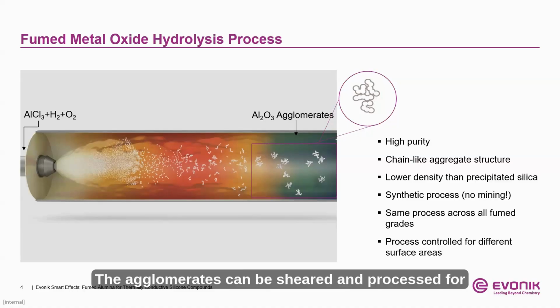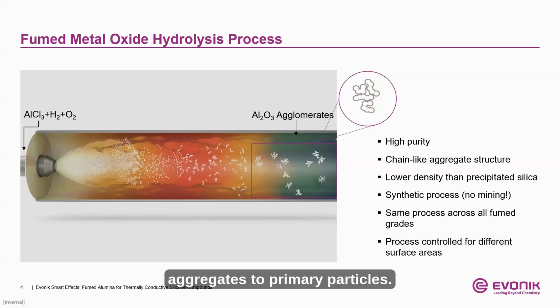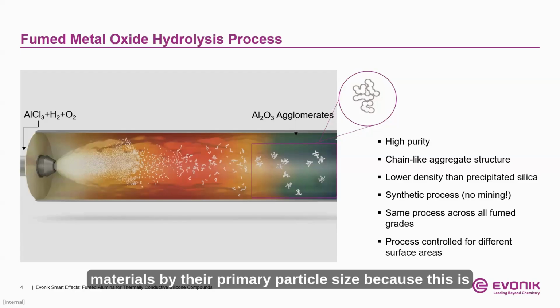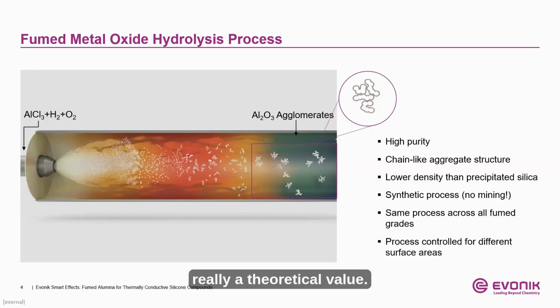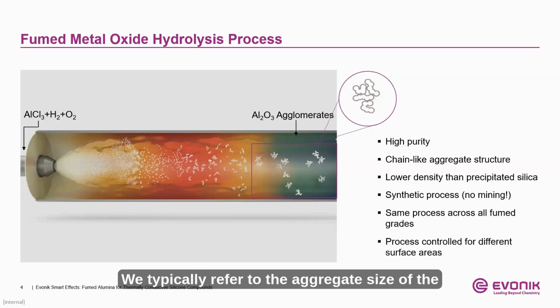The agglomerates can be sheared and processed for dispersion to break up the size of the agglomerates, but can never undergo enough energy to actually undo the sintering process I spoke of and reduce the aggregates to primary particles. So when we talk about fumed metal oxides, including fumed alumina, we typically don't refer to the materials by their primary particle size because this is really a theoretical value. We typically refer to the aggregate size of the material. We'll discuss this a little more in a few slides.